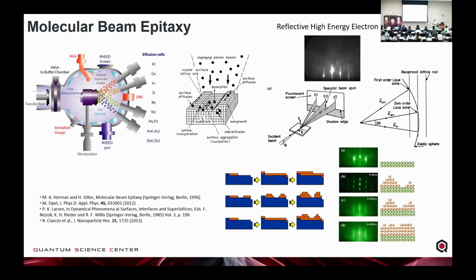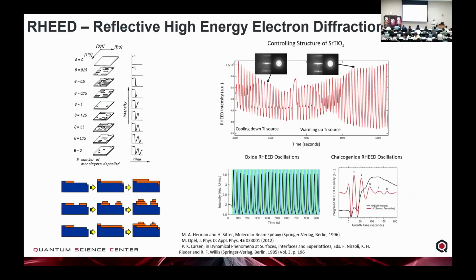And so looking at the RHEED can give us some insights into how they grow, whether it's going to grow layer by layer, or whether it starts to form islands, or if it has a step flow process. And so looking at the structure in the RHEED can give us insights into how these materials grow. And we can use that to better understand how to control the symmetries and the properties and the quality of the materials that we're trying to form. And so here, if a material grows layer by layer, you can look at the intensity of these RHEED patterns. And in a lot of situations, you can start to see oscillations as you form these materials layer by layer by layer.